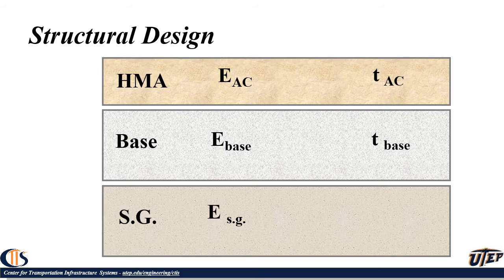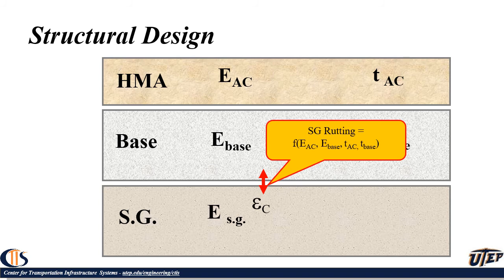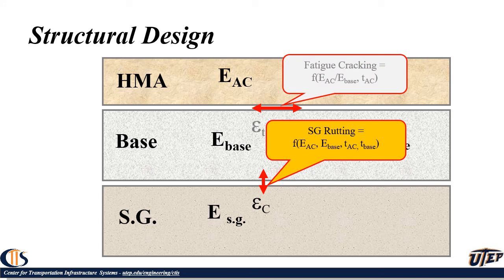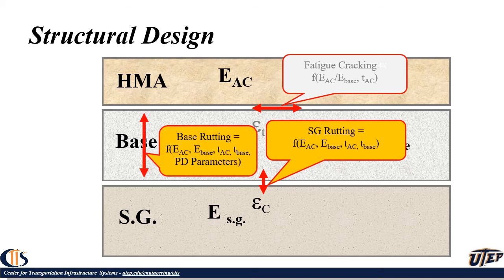The next step to consider was looking at the structural design. So we decided to see how we can start controlling the rutting and the cracking of the material. Traditionally, the cracking has to do with the tensile strength at the bottom of the asphalt, and rutting was the compressive strength at the top of the subgrade to make sure that the subgrade is not rutting. We were also interested in the rutting of the base. So basically, we started to use permanent deformation properties and a VESYS program to look at the permanent deformation of different layers.